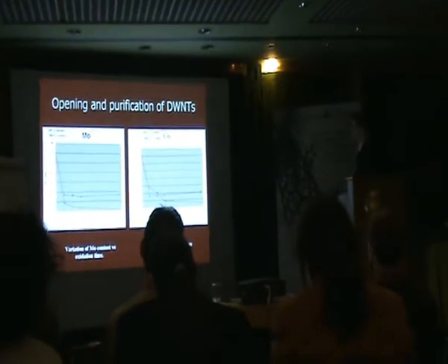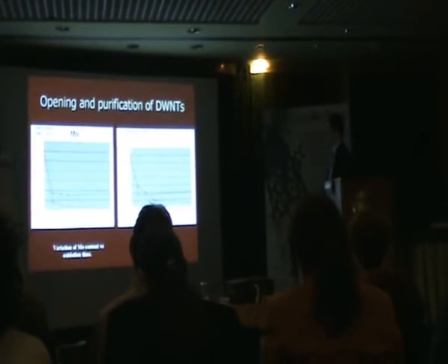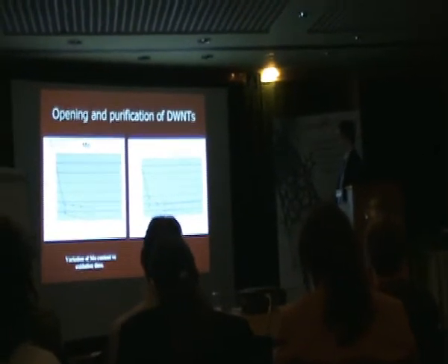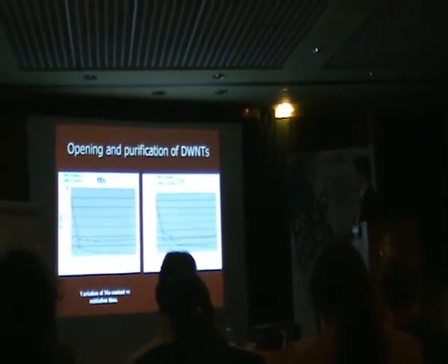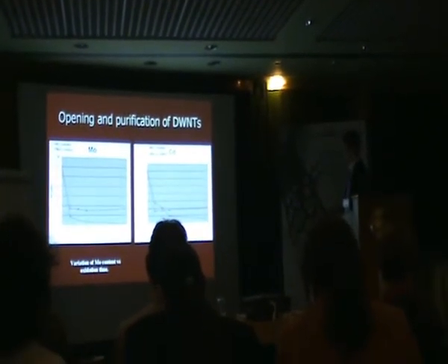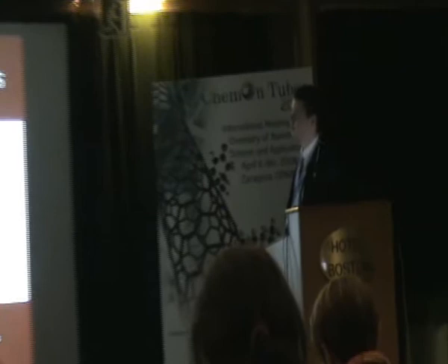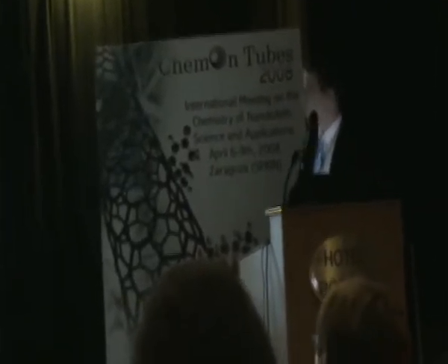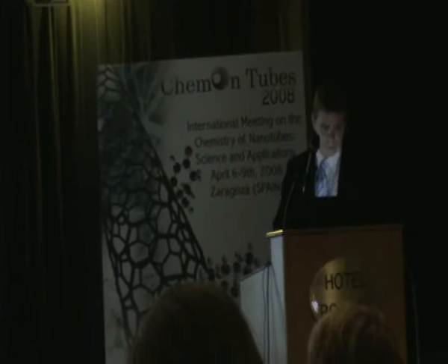The situation with cobalt is almost the same, the difference is just the quantity of cobalt after 3 hours and 6 hours. But finally, after 24 hours, we have a big decrease of cobalt, the same as in molybdenum. Of course, these metals are coming from catalysts, so we are trying to dissolve them with this oxidation.